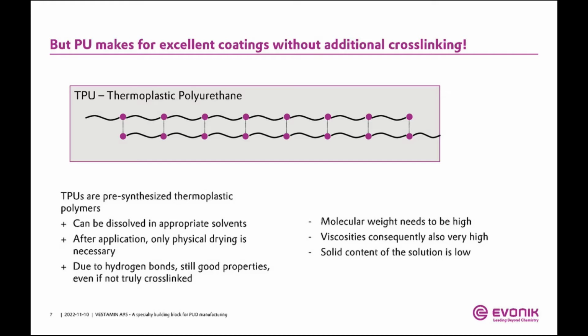Many of these coatings, many of these systems work very fine, but we have, of course, to take into account that we need relatively high molecular weights of these polyurethane chains for this system to work, and so that these properties, the chemical resistance, mechanical resistance, etc., stay on an acceptable level. And in order to get these relatively long molecular weight chains dissolved in an appropriate solvent, we either get very high viscosities, or we get very low solid contents. We have to dilute these systems very far so that they stay on an acceptable level viscosity-wise. So you have to choose either high viscosity or low solid content.